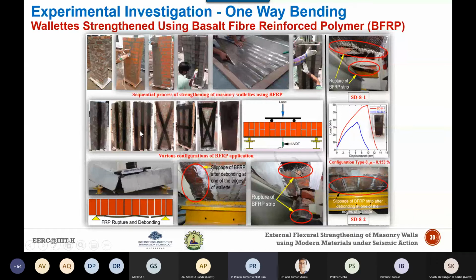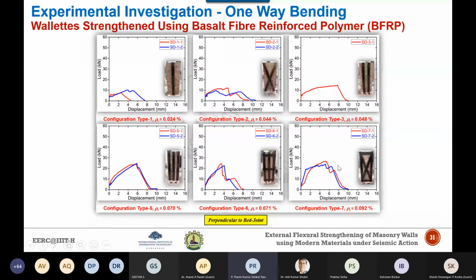What we did is we applied the first layer of the resin on the top of the masonry substrate where you want to adhere your FRP strips, and then the second layer of epoxy resin has been applied, and it was cured and left for almost 7 days under normal atmospheric conditions, so that the strips will adhere to the masonry surface and gain their strength. Now, when the specimens have been retrofitted using FRP, if you see their failure patterns, all the wallettes strengthened using FRP also failed in bending. No shear failure has been observed. These are some of the test results for the different configurations of the FRP specimens with respect to the increasing reinforcement ratio for perpendicular to bed joint.